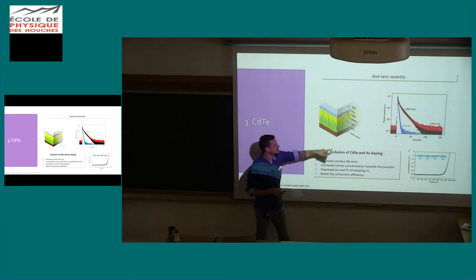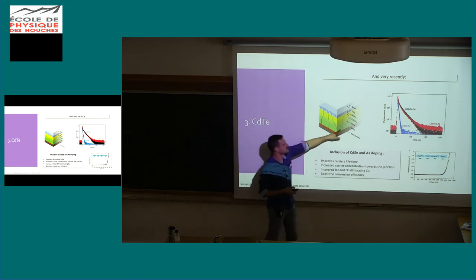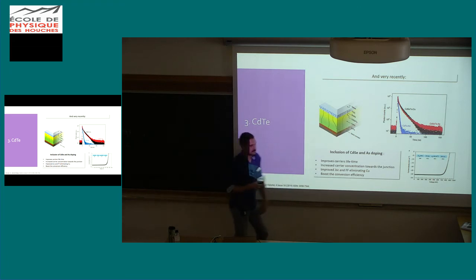So normally, what they do is to diffuse a bit, so you have some evolution from cadmium telluride to cadmium zinc telluride. So this kind of ternary compound, and then zinc telluride, and this is a gradual band gap change, and in zinc telluride it's easier to prepare an ohmic contact than in cadmium telluride. And this band gap gradient is a bit like in CIGS, where you...